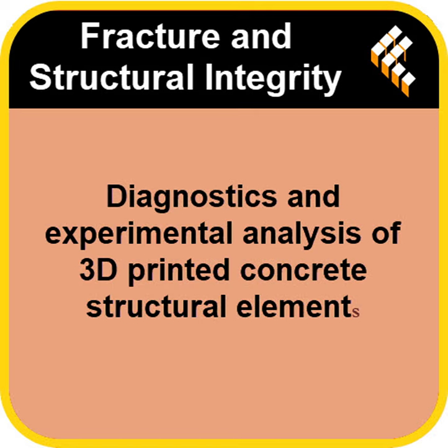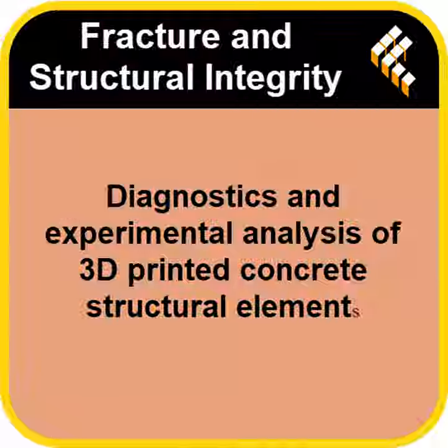Predictable. But the other 3 failed suddenly. And in a brittle way, the failure was total delamination. The layers just peeled apart. That's the nightmare scenario for structural engineering. So that variability, the peak load it could take, the stiffness, it was all governed by these tiny little printing defects. And the quality of that interlayer bond, the quality control issue, is literally printed into the material itself.